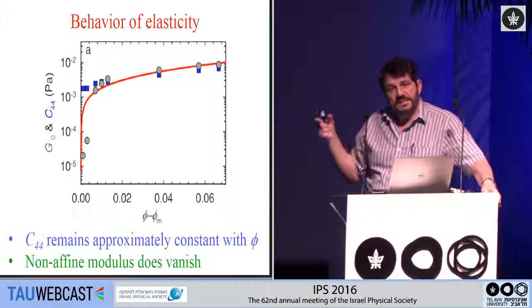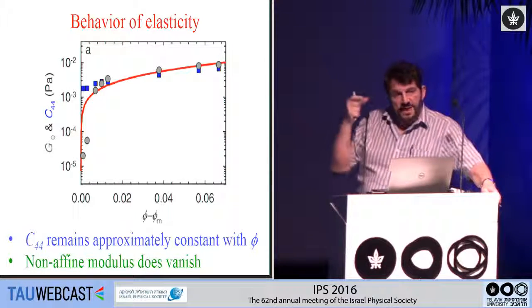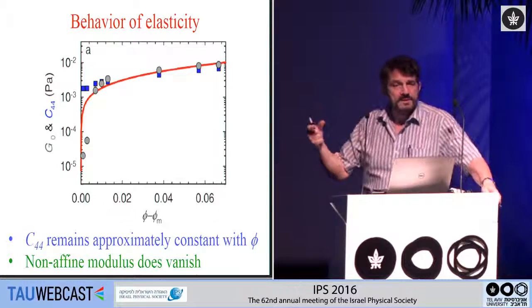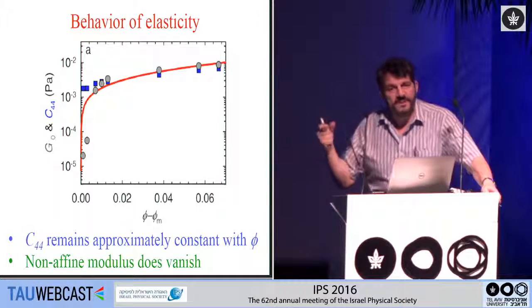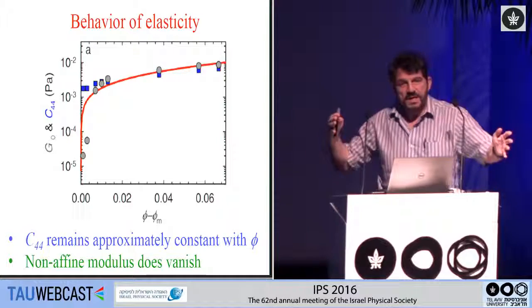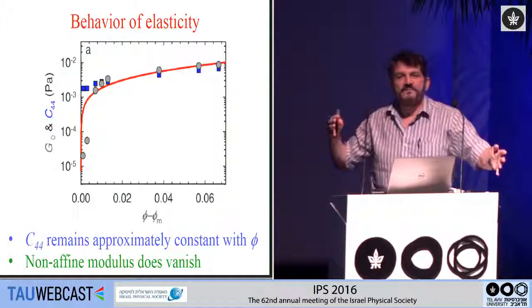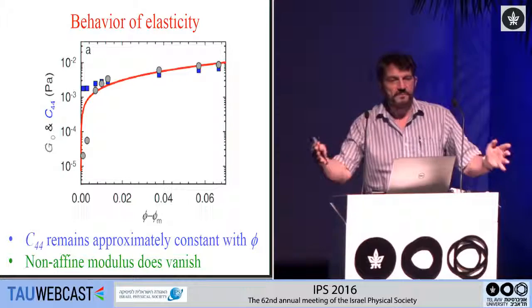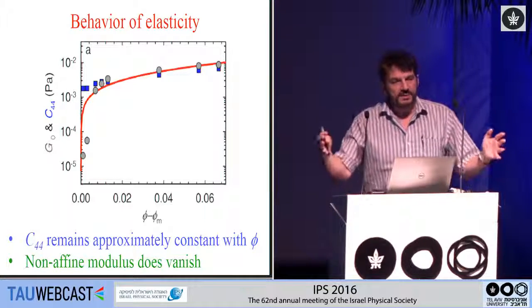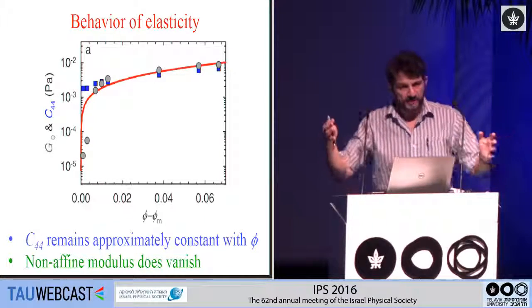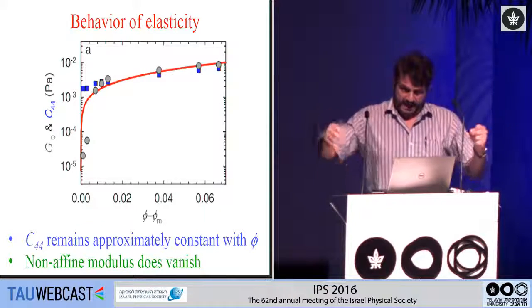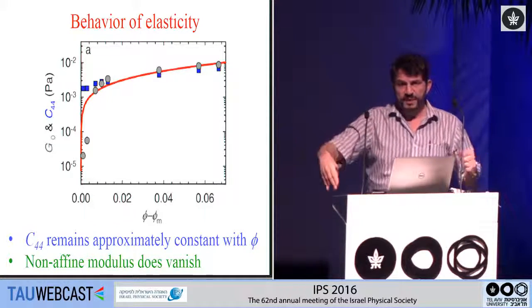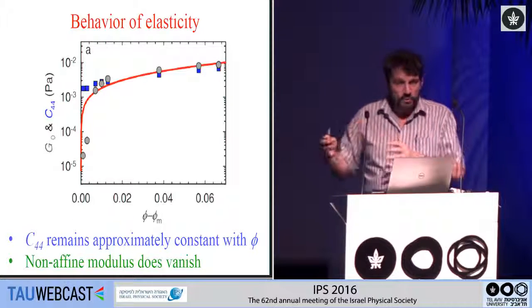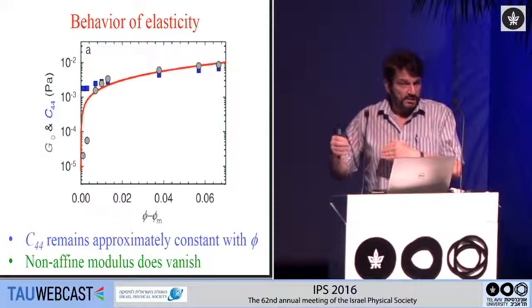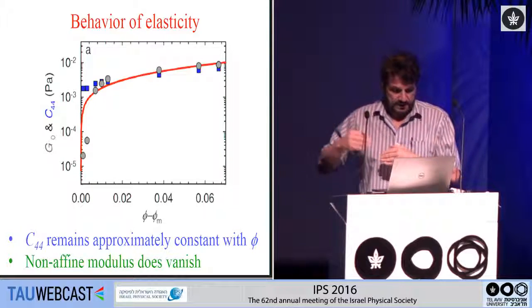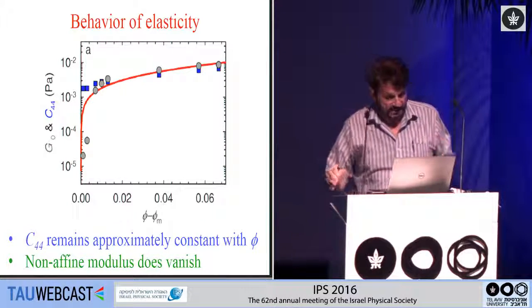So what this says is that the nature of the Born transition, the nature of the melting in the absence of interfaces, is that the sample can become very superheated because there's no way for it to melt. There's no way to nucleate the melting. Instead, the sample is perfectly ordered, it remains ordered, and it gets larger and larger fluctuations, and the degree of first order transition becomes weaker and weaker. That's why it begins to look like a second order transition.